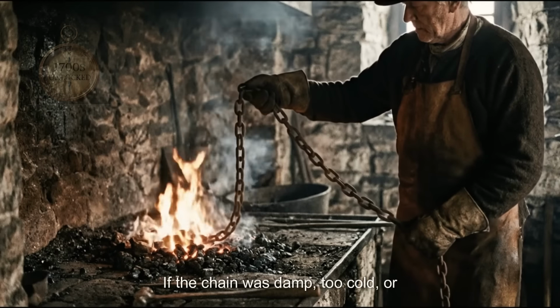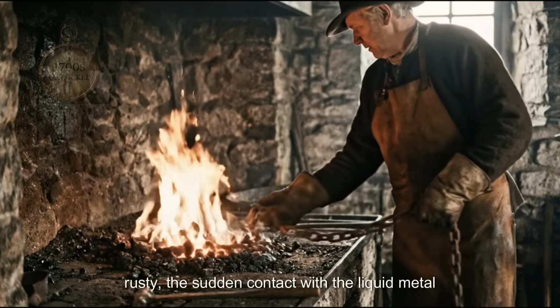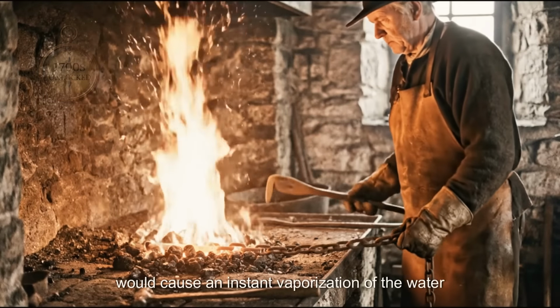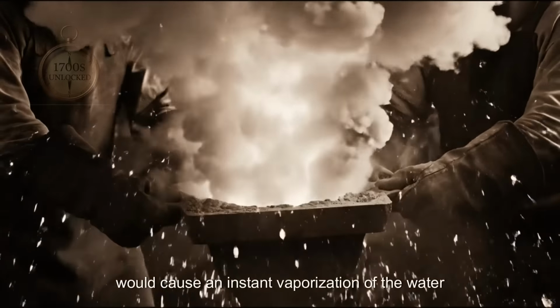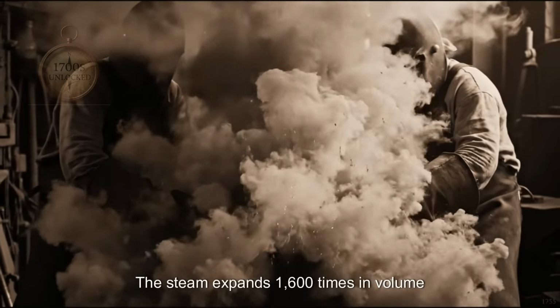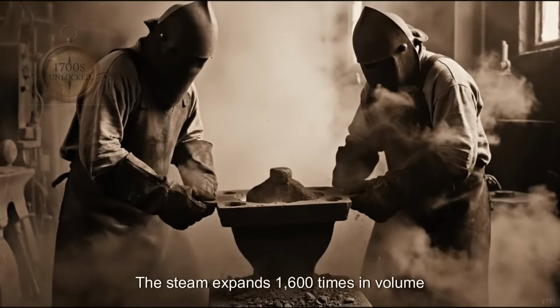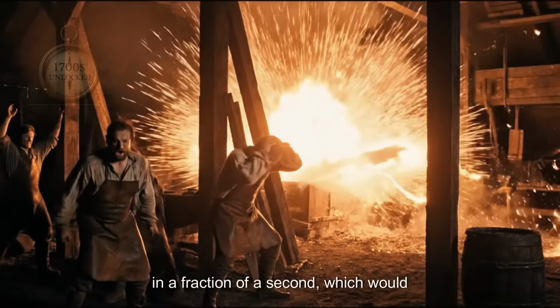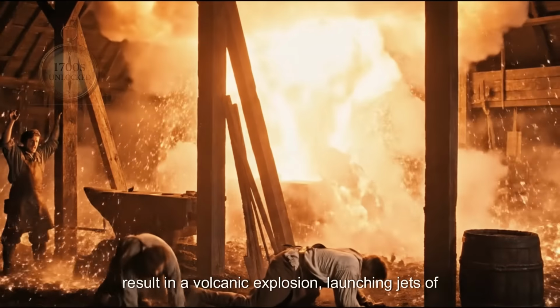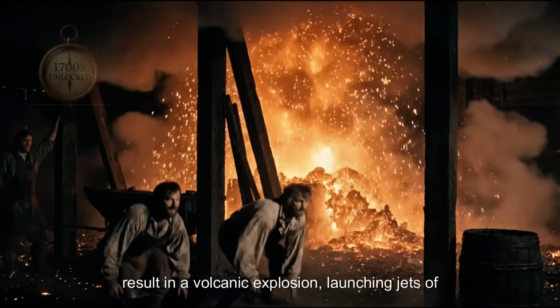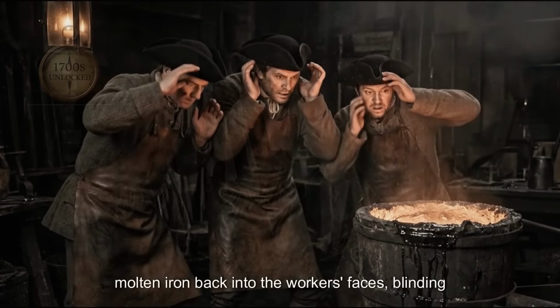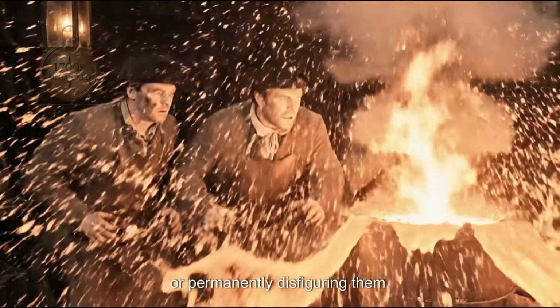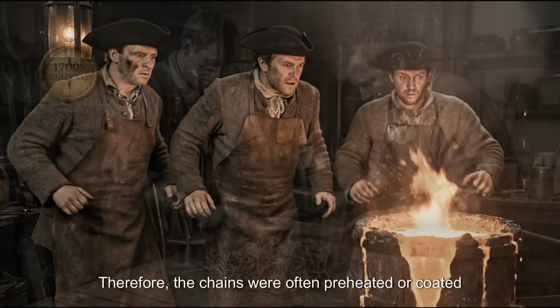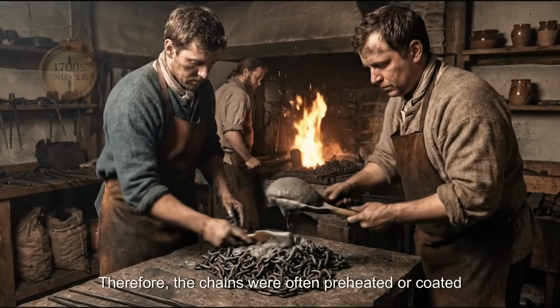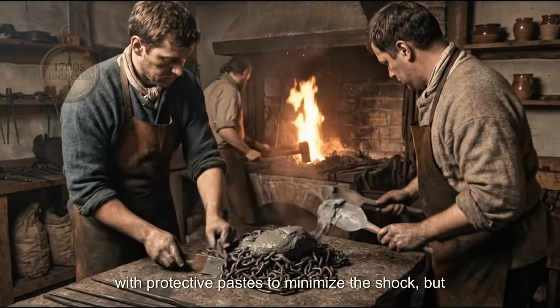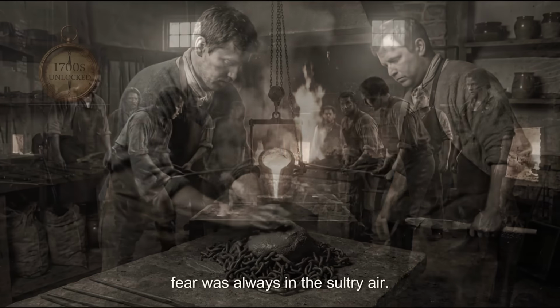If the chain was damp, too cold, or rusty, the sudden contact with the liquid metal would cause an instant vaporization of the water or oxides. The steam expands 1,600 times in volume in a fraction of a second, which would result in a volcanic explosion, launching jets of molten iron back into the workers' faces, blinding or permanently disfiguring them. Therefore, the chains were often preheated or coated with protective pastes to minimize the shock, but fear was always in